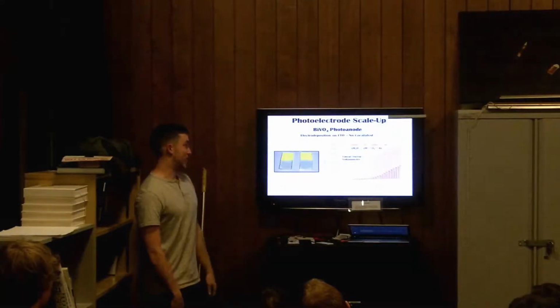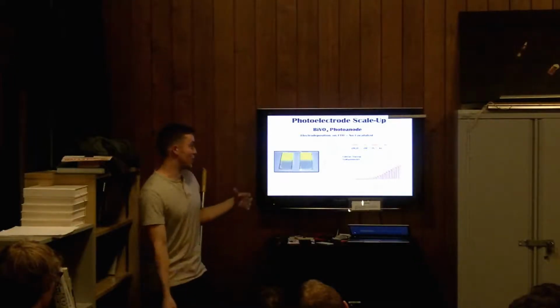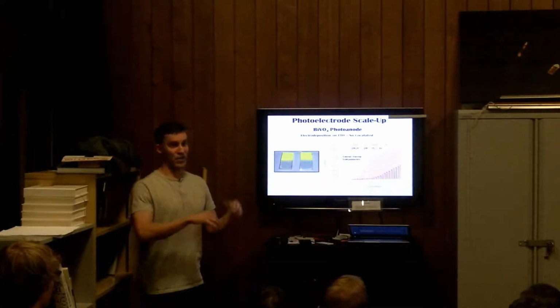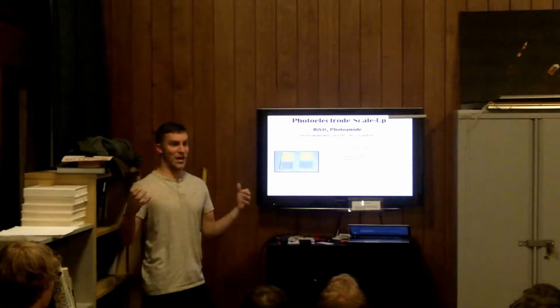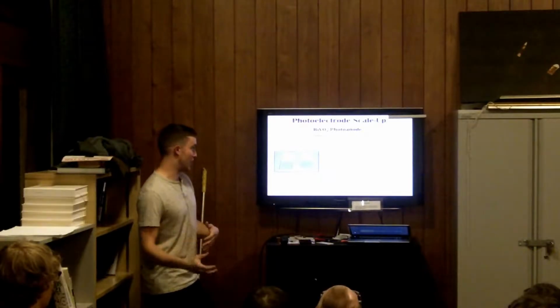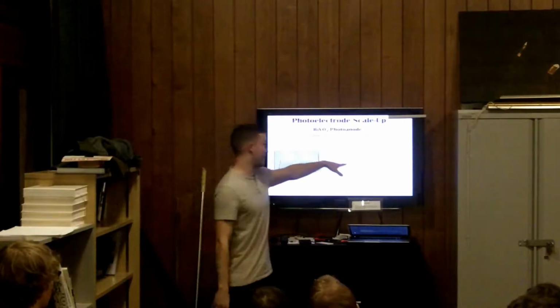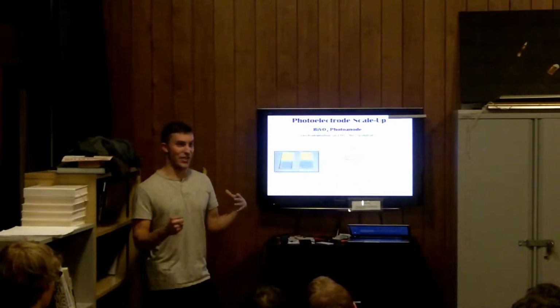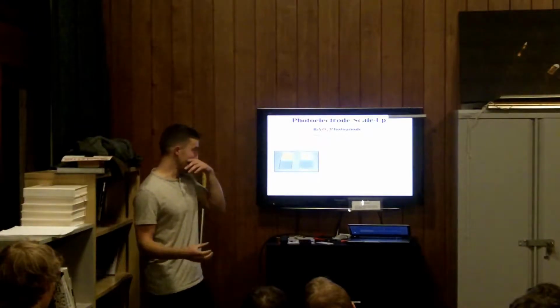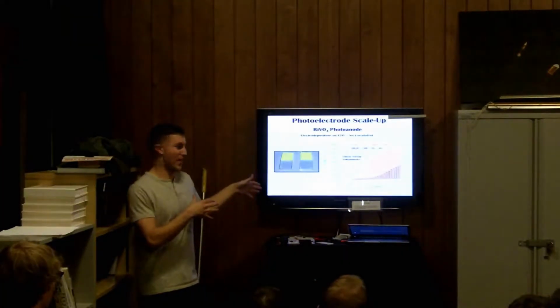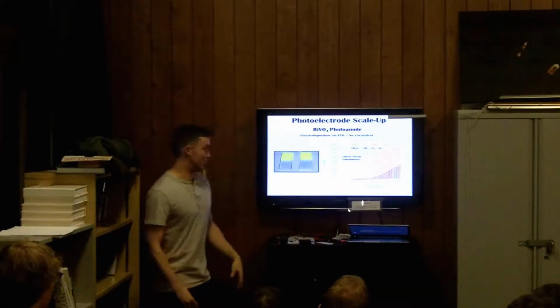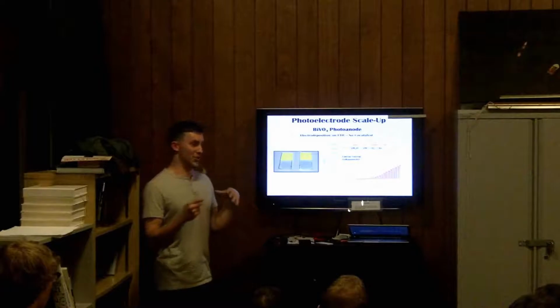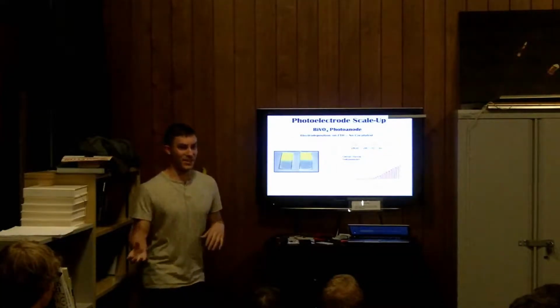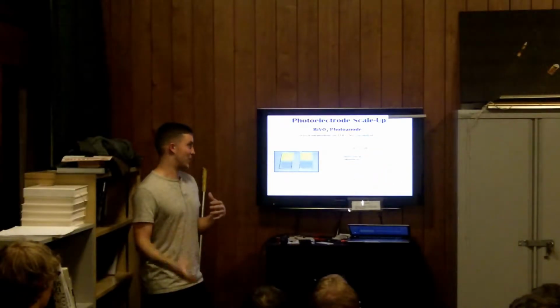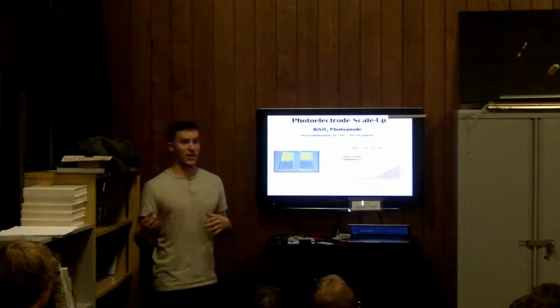And some of my actual results here. Again, I mentioned earlier that we use this technique called linear sweep voltammetry to show how much current we're actually getting out of our material, how much energy we're actually storing through the photoelectrochemistry. And the black line here is showing the water oxidation reaction and the currents that we're getting due to that reaction, which is similar to the data that I showed you earlier. This red line is due to the oxidation of sulfite, which is a reaction that we study because it's more easily conducted. The water splitting reaction is a very tricky reaction, actually. It involves a lot of electron transfer, and some of the catalysts aren't as great for that reaction as we'd like them to be yet.